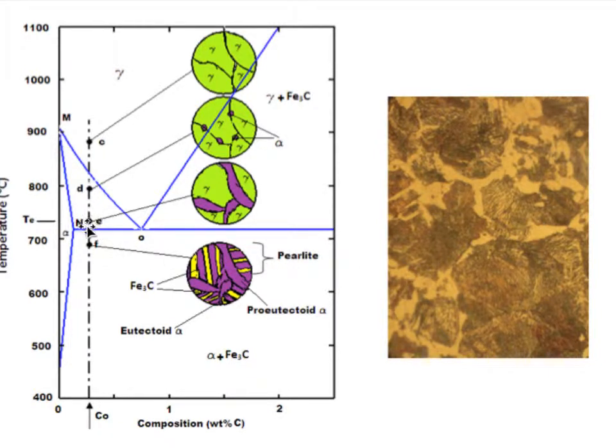But when we pass this line, the pearlite will form. So at this position, the carbon composition in the austenite has moved down here. When we pass this temperature, all the remaining austenite will turn into pearlite. As we see here, here we see pearlite regions. It's a large grain here and a large pearlite area.